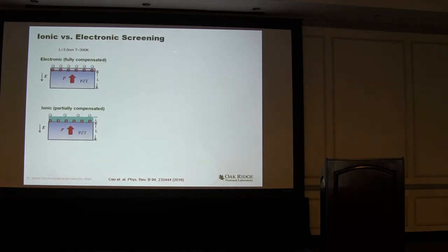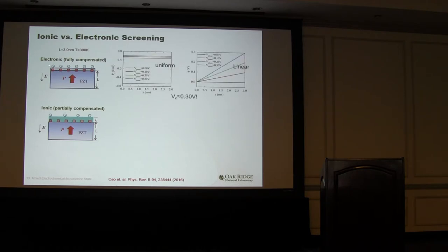And you might ask, so this ionic screening, what's the difference from full electronic screening? To do this, we compare the two cases where the polarization charge can be fully screened by the electronic carriers from the plate, or partially screened by ionic charge. In the full electron screening case, this behaves like a single domain behavior, with polarization uniform in the system, suppressed uniformly when increasing the applied bias. And the electrical potential is linear from top to lower